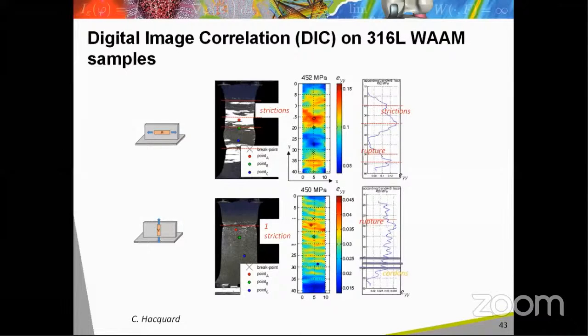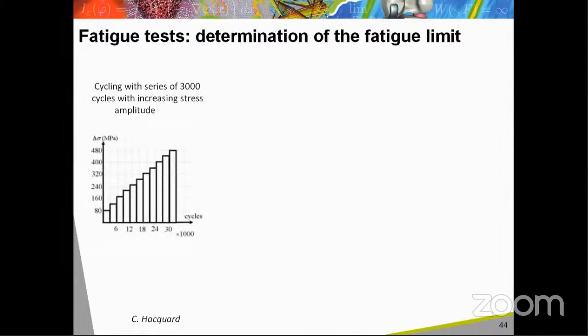Another mechanical property that can be unconventional in WAAM materials is the fatigue behavior. Some first fatigue tests were achieved also on 316L stainless steel samples, and only the fatigue limit has been studied for the moment. To estimate this limit, a method based on the measurement of the heat dissipation of samples submitted to a given stress amplitude is used.